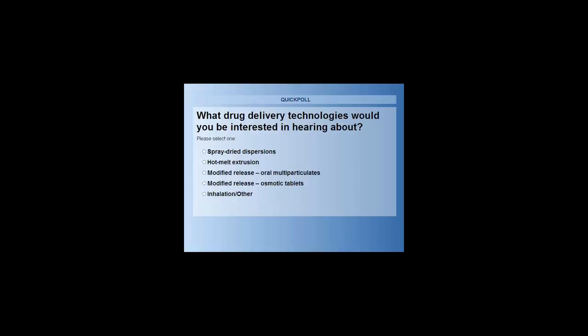Thank you. And is Tg in slide 14 of pure drug or dispersion, and what about the Tm? Yeah, that's the Tg of the dispersion. So again, you would use differential scanning calorimetry to measure the Tg of the dispersion as a function of humidity, and then that's used to determine the Tg over T. In this case, the T just refers to the temperature being held in the experiment, the TAM experiment. So melting point, in fact, is not directly used in this analysis.